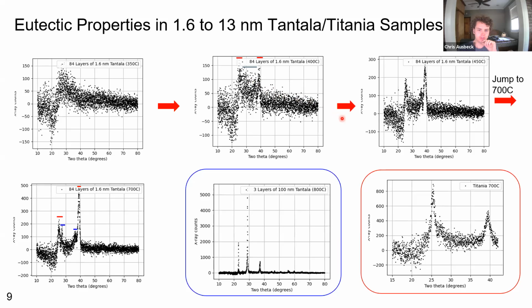As we go to higher temperatures, though, these mixed crystal lattices tend to go away. This is at 450 C, they start to decrease. And then at 700 C, they decrease more, and you can barely see them. We've also seen that these two main titania peaks around 26 and 39 degrees are still present. We also see the tantala peaks. They're very small and very slight, but we see them here at around 29 degrees and around 36 degrees.